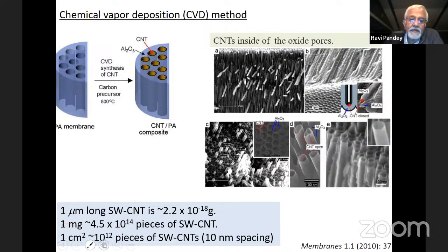And if I look at a 1 centimeter square area, with some defined spacing for a given device, we have to have about 10 power 12 pieces of single walled carbon nanotube. So this gives an idea of going from lab scale to manufacturing scale. One has to be very, very careful in providing such a large quantity of nanotubes without any defects. And that's a challenge which industry is facing.